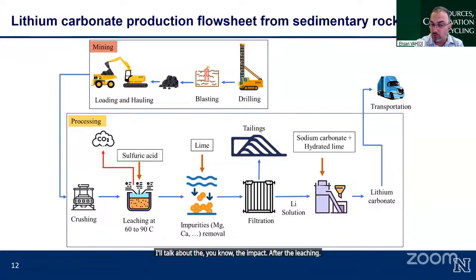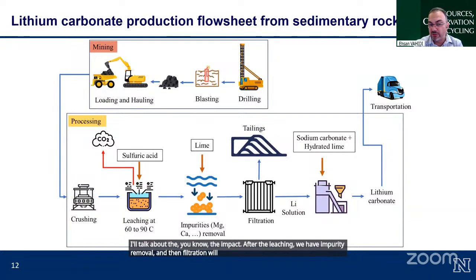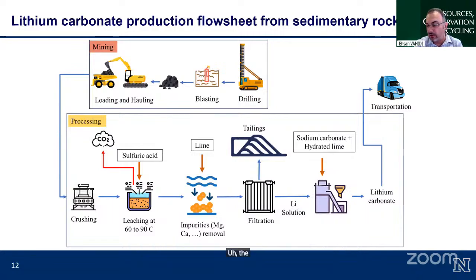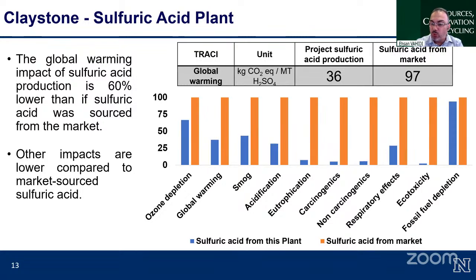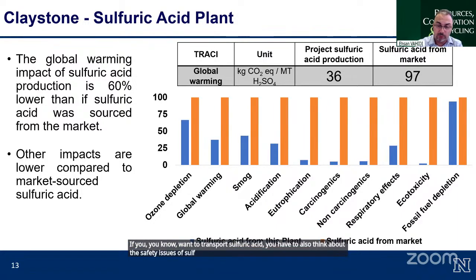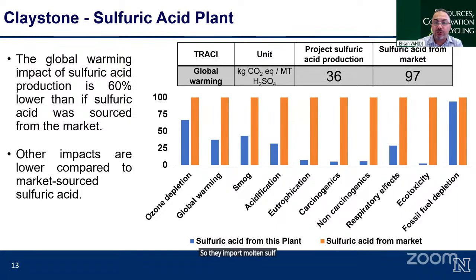After the leaching, we have impurity removal, and then filtration will send the filter cakes to the waste, to the tailing process, and also after the final impurity removal stage, we can have lithium carbonate equivalent. When we have sulfuric acid consumption in this process, we can produce sulfuric acid on site. So this is the approach that most of the lithium production facilities is choosing right now in Nevada. Most of them are in the middle of nowhere. So they prefer to import molten sulfur instead of sulfuric acid because of different reasons. So if you want to transport sulfuric acid, you have to also think about the safety issues of sulfuric acid. So this is another problem. So they import molten sulfur and they produce sulfuric acid on site.